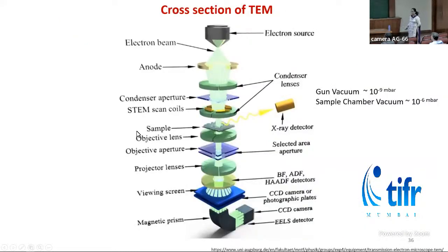Here is a cross section of TEM. This also has a gun, an electron source, and then the electrons are accelerated down by the anode. It has condenser lenses to form the fine probe, and it has scan coils where the beam can be moved across the sample. As I mentioned, in case of TEM, the image is formed by the electron beam which is transmitted through the sample. So here the sample sits, and below that there are further lenses, projector lenses, to